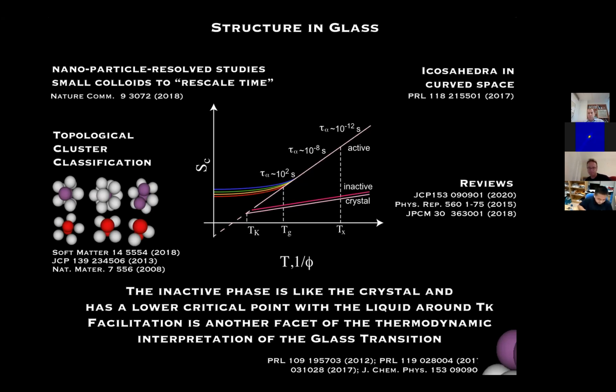Yeah, but my question is, if you don't have any local preferred structure, there's still, in my opinion, a lot of polyhedra that can fully fill the space. If you want to pack them, even a small cluster, they don't prefer any local thing. They prefer the global crystal structure. In that sense, is this perspective of a local cluster for the glass transition still applicable in this kind of system? Because I think the polyhedra can easily become stuck somewhere and look like glass.